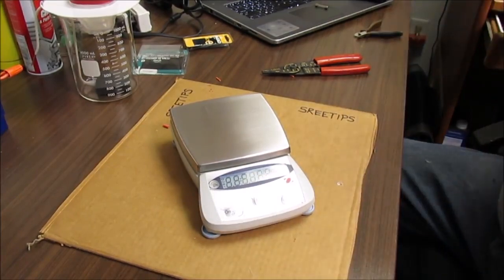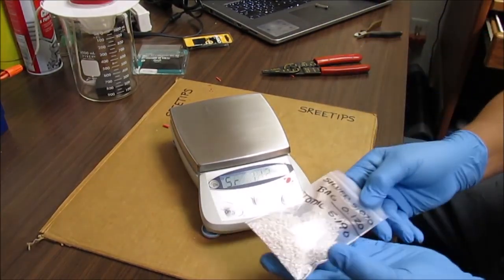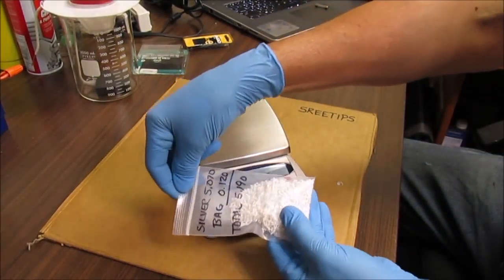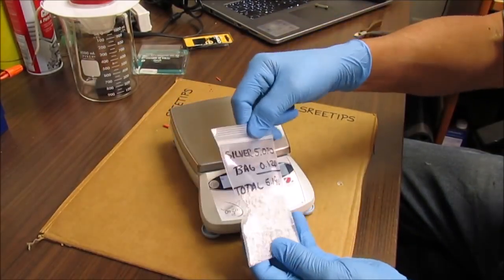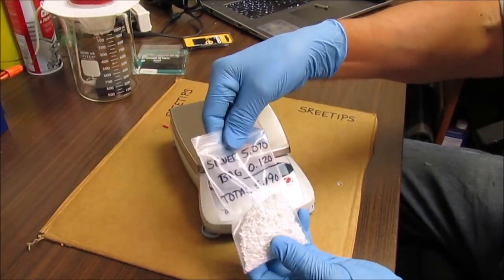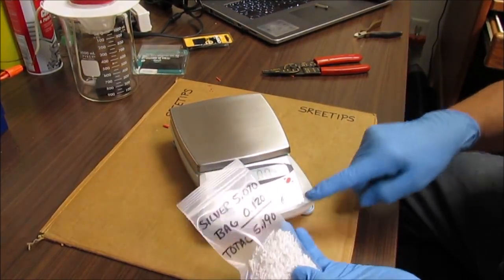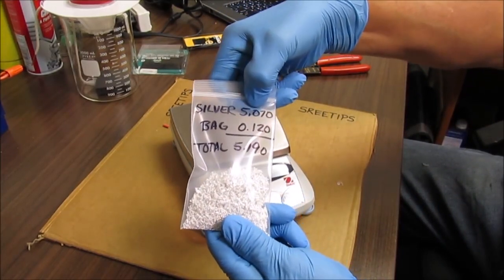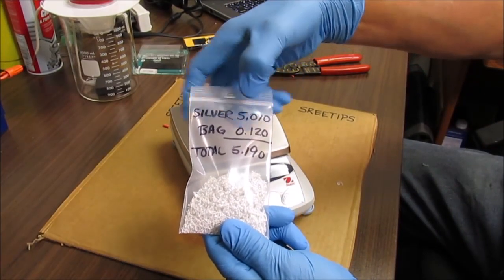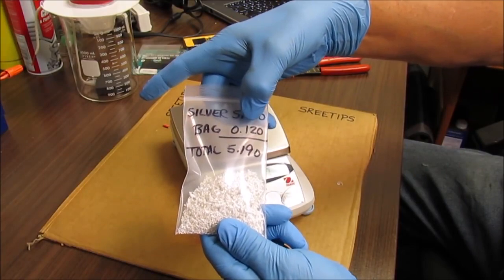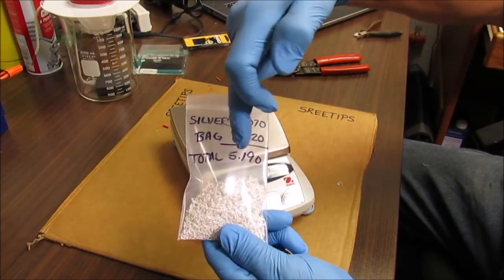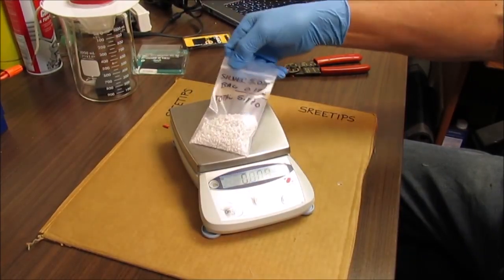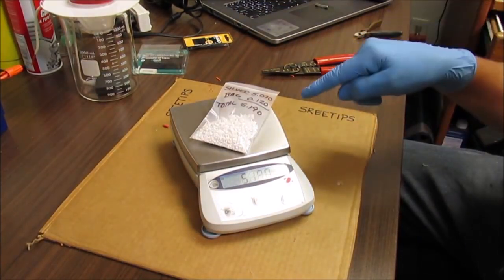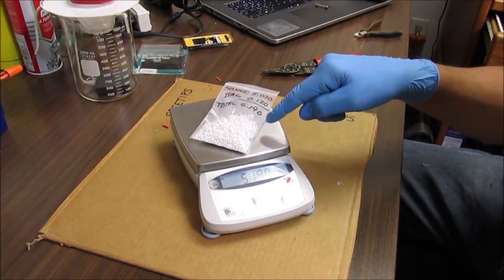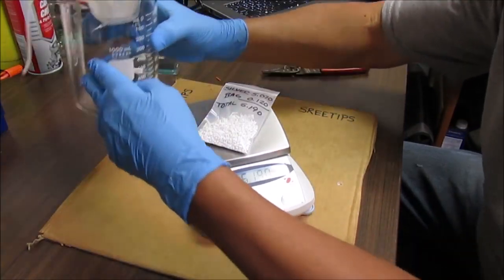I've got a scale here, and I've got a bag of pure silver crystal from a previous refining. This is 5 troy ounces, or about 156 or so grams. If you put it on the scale here, I've got it marked. It's 5.07 troy ounces of silver. The bag weighs 0.120 troy ounces. The total will be 5.190 troy ounces. And I'll use this silver for the electrolyte for the silver cell.